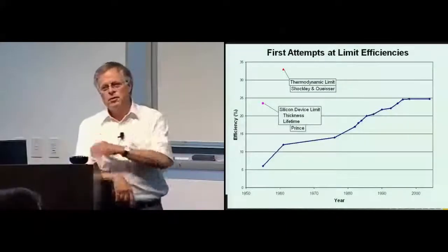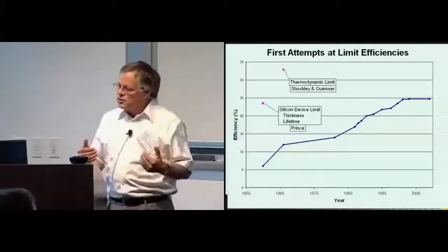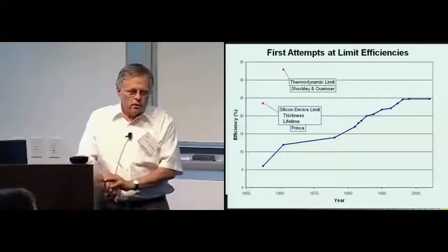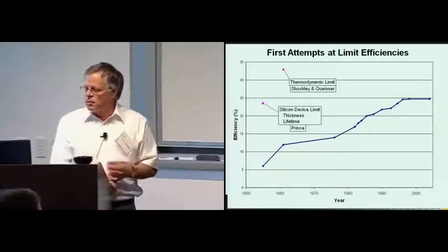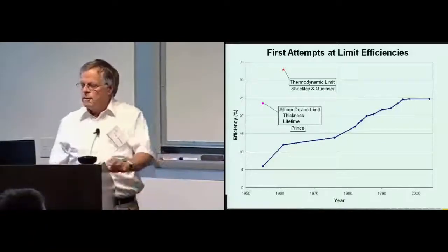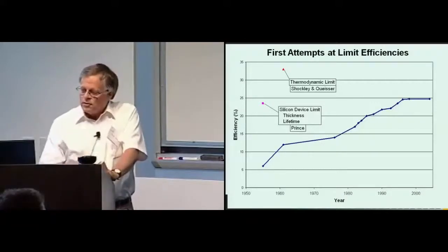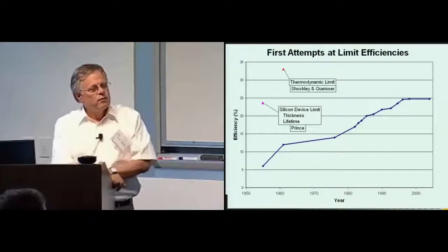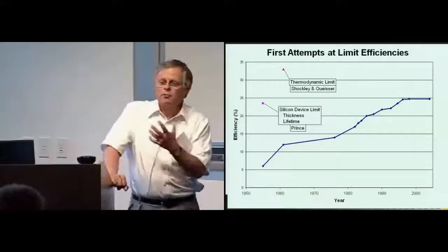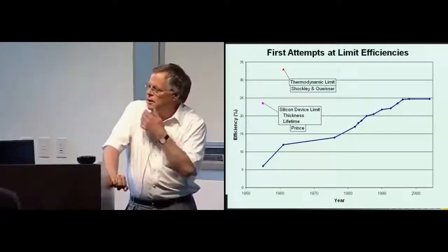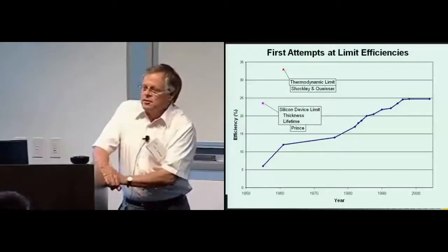Of course, this is pre-computer models, so they did analytic models, but they plugged those in there to try and see how well a solar cell should work using your standard semiconductor device equations. And the first guy to really do that to any degree was Mort Prince in the late 50s. And he came up with, if you sort of idealized everything in the semiconductor device model, that it would be around 24% conversion efficiency. Notice that the actual experimental results have exceeded that.